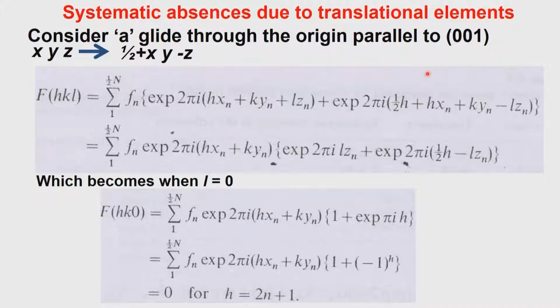So, the space group, the lattice type we have seen. Now, let us say there is a space group which is associated with an A glide. Let us take an example of a primitive lattice with an A glide. It could be an I-centered lattice with an A glide in a monoclinic system, or say the centering could also be a reason which is introducing the A glide.